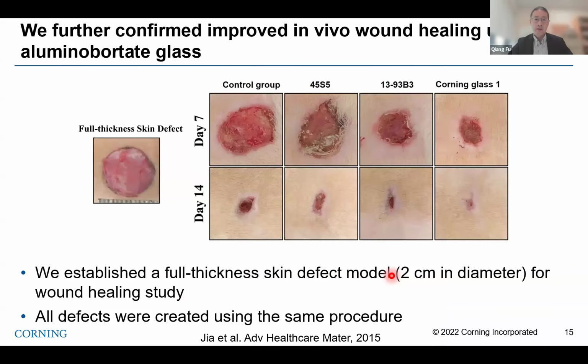So what we did here is we designed a new composition based off aluminoborate glass. We did a work using 45S5 and 13-93B3, which is the borate version of 13-93 glass. We used these as controls and compared with our own composition. We used a full thickness skin defect model with a diameter of 2 centimeters for this study. We found our composition shows better performance than either 45S5 or 13-93B3, the glasses Steve and Dimple used a couple years ago.